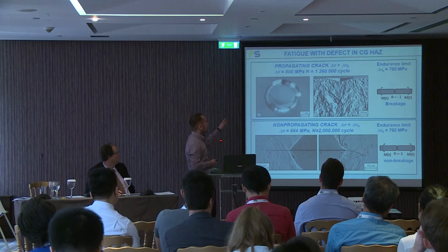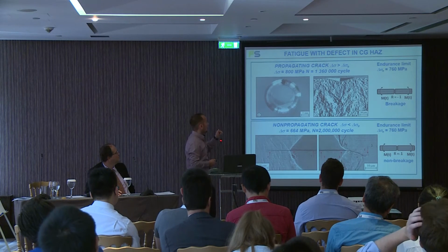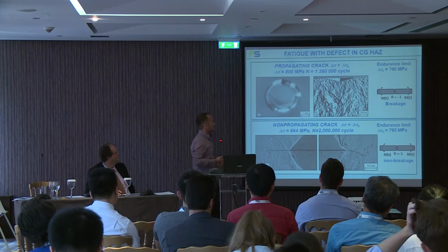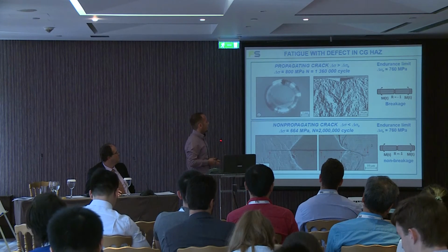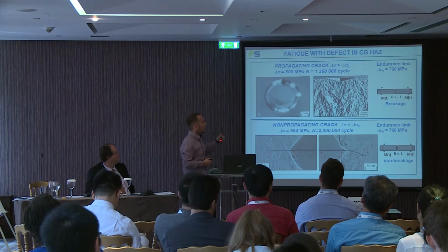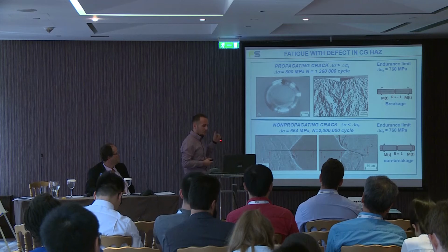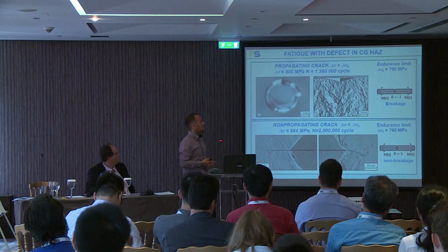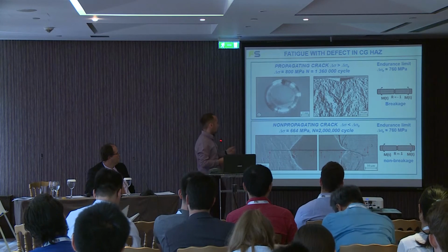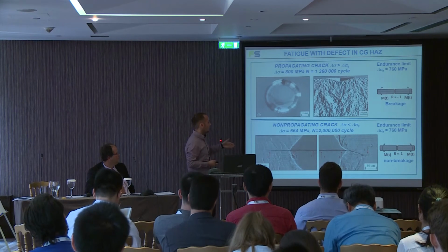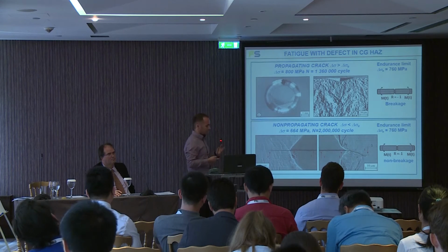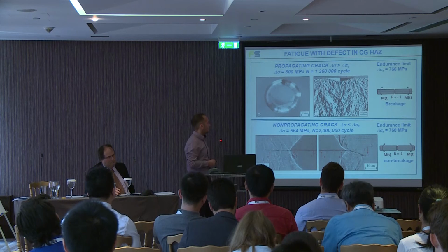microstructure and breakage. We have breakage at 800 megapascal and 1,360,000 cycles. The endurance limit for the coarse grain specimens was 760 megapascal, and the non-breakage specimens have survived only under 664 megapascal.